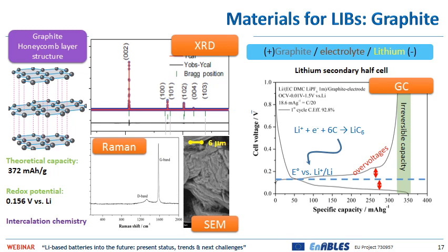There's a second feature that is very important to consider, that is the occurrence of irreversible capacity. Irreversible capacity is the difference between the charge in discharge and the charge in charge, and this is due to the occurrence of parasitic reactions. In fact, at such a low redox potential, very close to the one of lithium, there is no aprotic solvent that is thermodynamically stable. All the solvents that constitute the electrolyte of the lithium-ion cell are reduced at this very low potential. This reduction is a parasitic reactivity and takes place unavoidably on the surface of graphite.